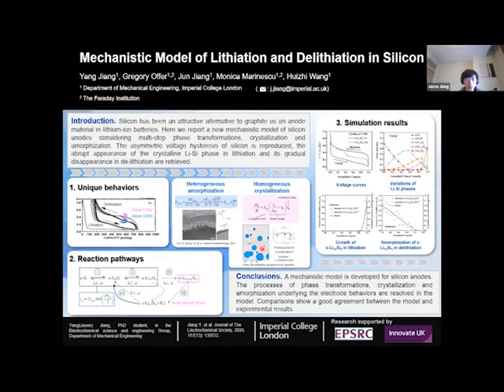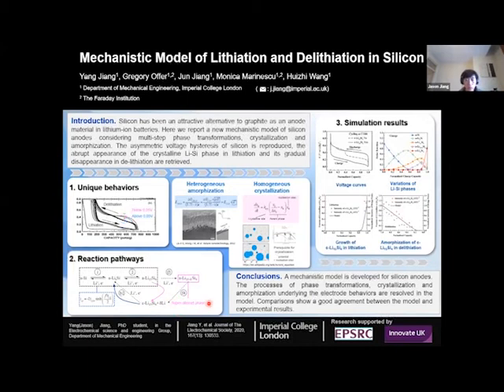A homogeneous crystallization theory points out that as the amorphous silicon phase transforms to its crystalline phase, we assume that a kind of super-alloyed phase is formed which provides the nucleation sites. The kinetic equation shows that the crystallization growth rate is proportional not only to the amount of the amorphous phase, but also to the nucleation sites.